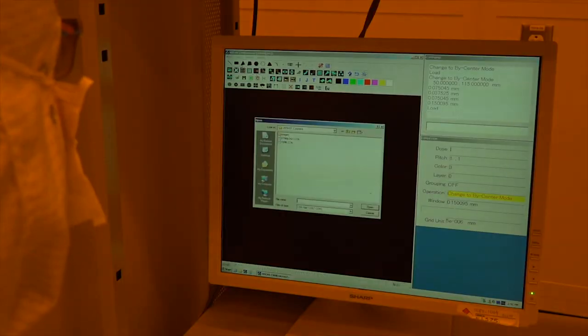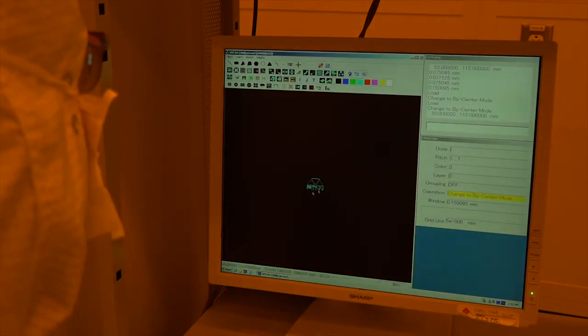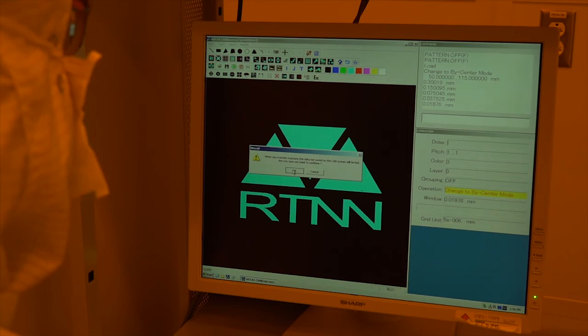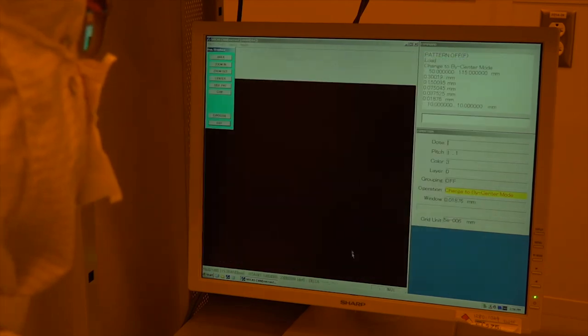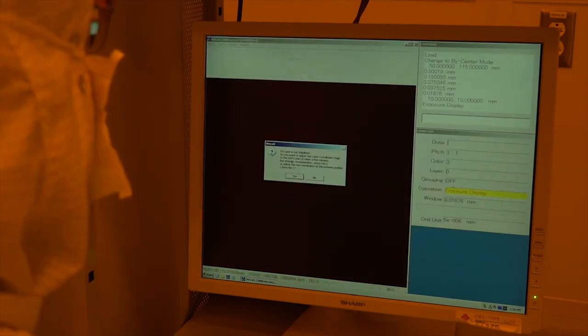Now we load our CAD file that contains our pattern and set the exposure time. For this particular pattern, we choose 2.6 microseconds for the exposure time. We are now ready to expose the EBL resist on the wafer.